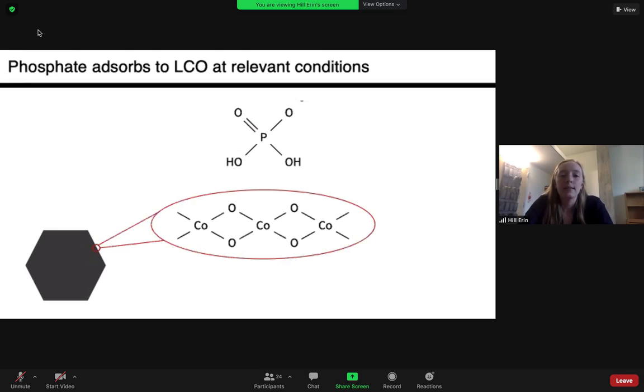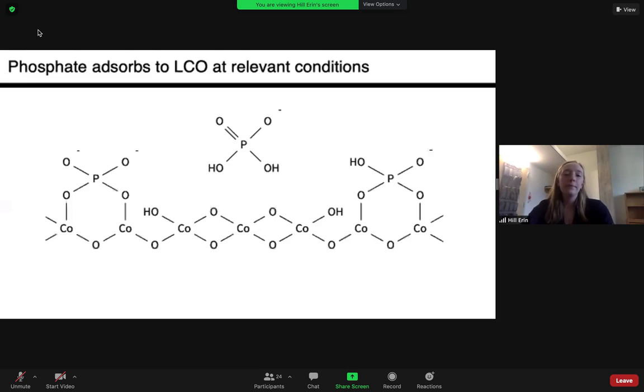Now that we've analyzed the IR spectra, you can put it all together to figure out how phosphate interacts at the surface of LCO. And we can confirm from the IR data that phosphate interacts strongly and irreversibly with LCO at environmentally relevant conditions. We determined that there were 3 main ways that phosphate interacts with LCO.